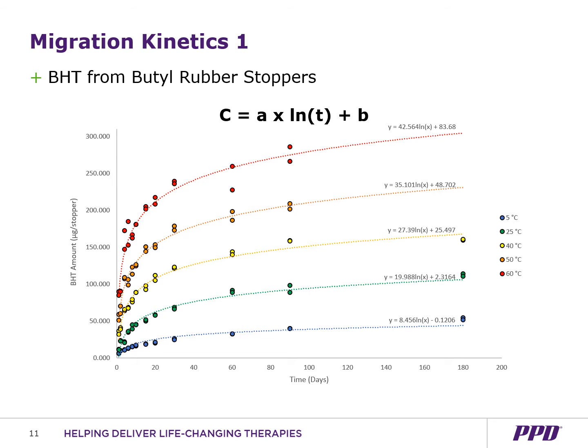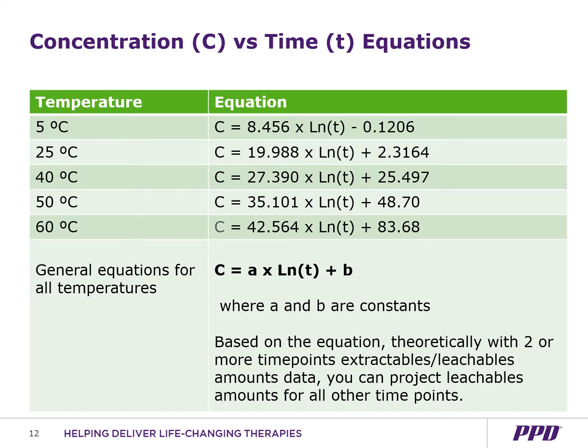So from the curves, we were able to develop a general equation shown in bold there, where C is equal to a constant A times the natural log of time plus a constant B. So here is a summary of those general equations we gathered from each of those plots to make a general equation, where C equals the extractables or leachables concentration or amounts. A and B are constants that can be derived from the existing time points data, and T equals time. So for this, theoretically, with two or more extractable and leachable time point amounts, you could project the leachable amount for future time points.